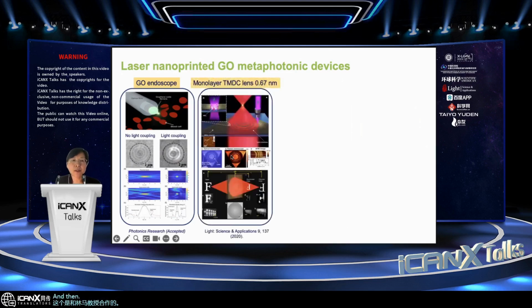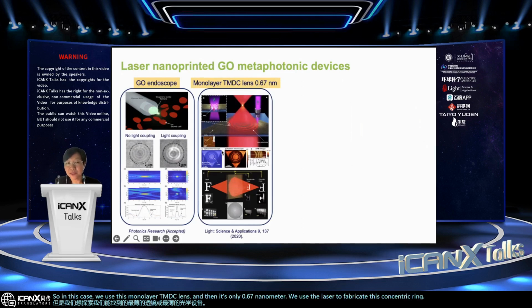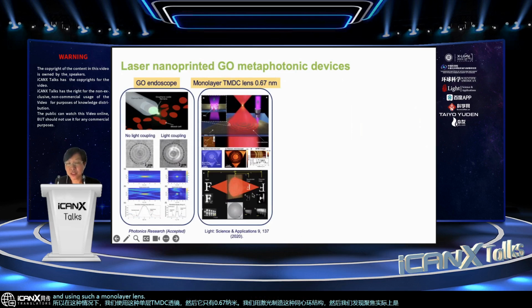And then we also would like to see, because this method, we are working on really, really thin layer of materials. So previously it's all on the like 100 nanometer scale. But then we want to explore, so what's the thinnest lens or thinnest optical device we can fabricate? So in this case, we use this monolayer TMDC lens, and then it's only 0.67 nanometer. We use the laser to fabricate this concentric ring structure, and then we found that the focusing is actually really, really good. And using such monolayer lens, we're able to achieve the imaging of some characters, first order and second order imaging with high resolution.